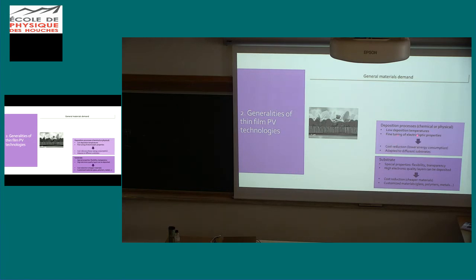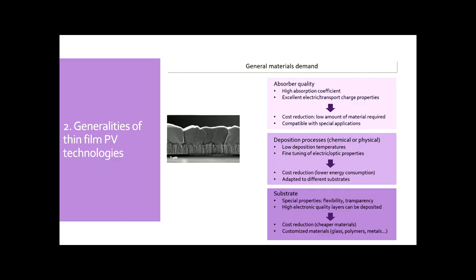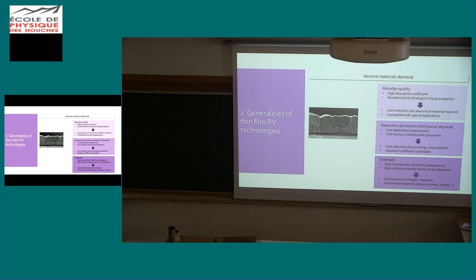Then, the use of lower deposition temperature allows for cost reduction, lower energy consumption, and adaptation to different substrates because we are working at lower temperature. And finally, we need the absorber to fulfill some standards. We need high absorption coefficient and excellent electric and charge transport properties. And thanks to the very high absorption coefficient, we can use a low amount of material, and this implies a cost reduction, and is compatible with special applications, because using this type of substrate, we can convert our devices into transparent, semi-transparent, flexible, and all of this is almost impossible for silicon.